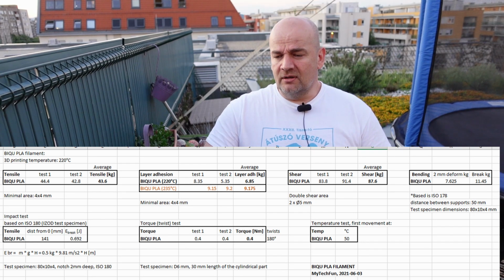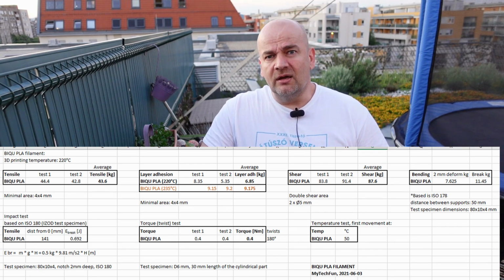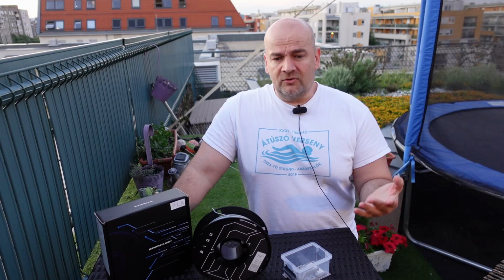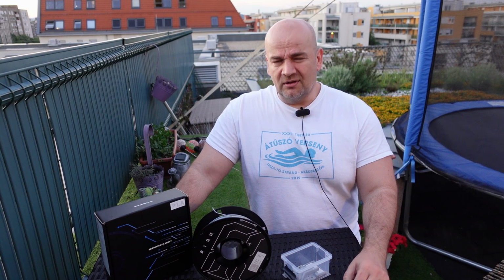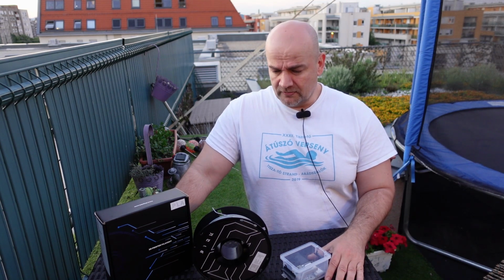And I believe that the reason in every case is the weaker layer adhesion. You saw I even tried to print it at 235 degrees Celsius, which is 15 degrees above the recommended printing temperature, but even there I got quite weak layer adhesion. I mean, sometimes this can be an advantage because it is easier to remove the supports, but I think in most cases this is not a requirement for most users.